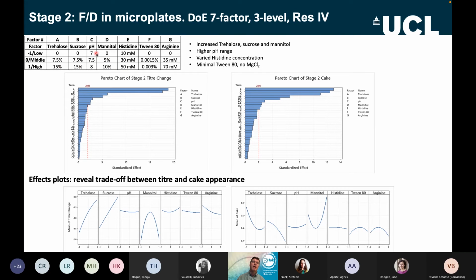Same with mannitol. We shifted the pH to a slightly higher range, and we also eliminated one of the buffers and just fixed histidine and looked at the concentration of that, and also Tween. We kept arginine and we got rid of magnesium. So some changes, but mainly to explore higher concentrations. We performed exactly the same freeze drying in microtiter plates, and you can still see trehalose is important in terms of titer change. Sucrose is important. Mannitol has a self-interaction, DD, which is because it has an optimum in the range. So we can see that there is actually a point where mannitol becomes a negative impact on titer. So mainly trehalose and sucrose and mannitol, with a little effect from arginine.